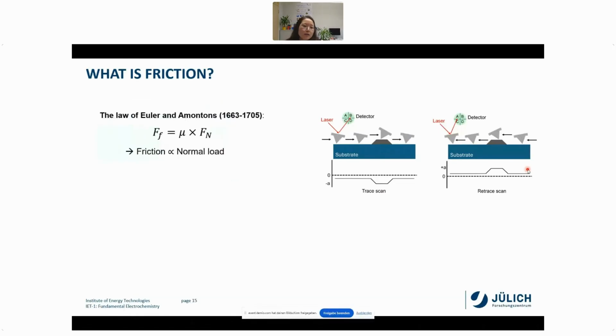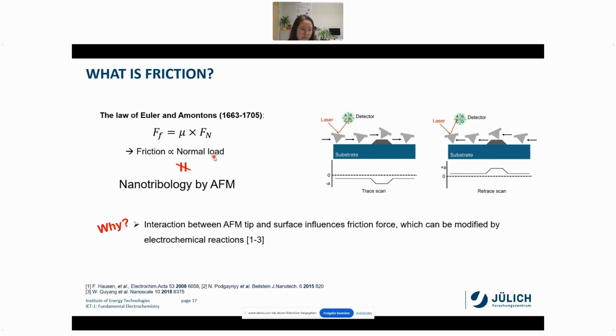Then, this equation you might have seen already in middle school or high school. The law of Euler and Amontons explains that friction is proportional to the normal load. However, this is not always true, especially for nanotribology measured by AFM. Why? Because there is an interaction between the AFM tip and the surface, which can be modified by electrochemical reaction. So for better understanding, I will tell you the other way around. If there is some change of interaction at the surface, then it can modify the interaction between the AFM tip and the surface. Therefore, friction will not be all the time proportional to the normal load.